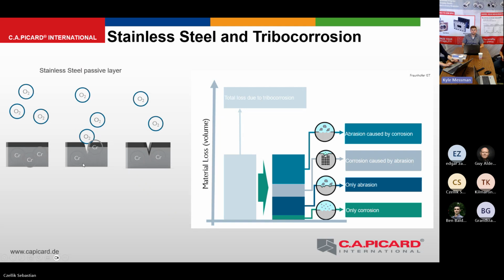Because the chromium always has to get to the surface by diffusion, and if you do that too often, there's not enough chromium left near the surface. And that brings me to my next point. I want to explain that we mainly, or often, have tribocorrosion.